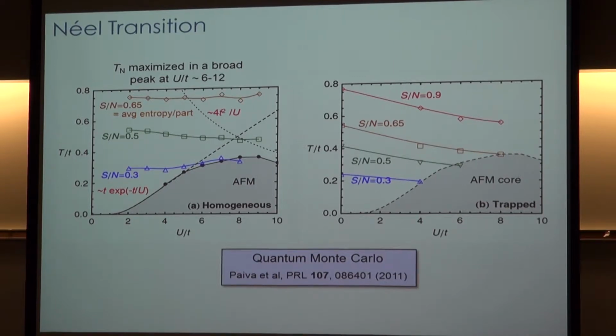And so on an entropy per particle basis, the entropy that you need to cross into this antiferromagnetic phase is considerably higher than it is for the homogeneous case, by about a factor of 2. So this is something to keep in mind. This is our goal, to be able to get entropies of order 0.6 or so.